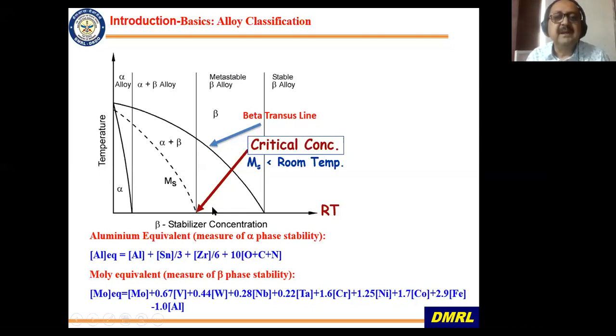And the beta alloys, by their name, you can see it is just beyond the martensitic start line. So that means if you heat treat in this region and quench it fast enough, then you should be able to retain the beta phase at room temperature. So that is why these alloys are known as beta alloys. And then you can age them to very high strength levels, and that is how beta alloys are designed to be used. So this is the classification in brief of the conventional titanium alloys. We'll look into another category, which is the aluminides, later on, which is not here.